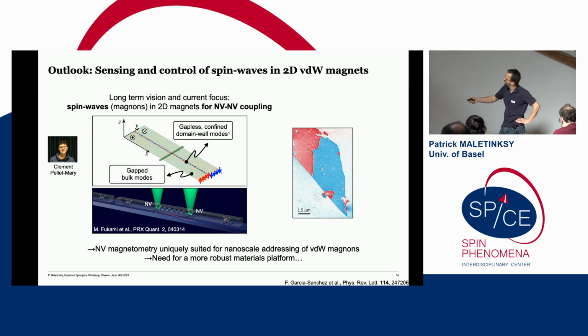So one goal we have here is to engineer waveguides for spin waves. It has been long known, also in more classical magnetism, that domain walls can actually act as such waveguides if you're dealing with a magnet with strong uniaxial, very anisotropic material. Then you have strongly gapped magnon modes in the bulk, but a non-gapped mode here in the waveguide, and this can then propagate along this domain wall. And of course, the long-term vision for this is to use this to couple remote NVs.